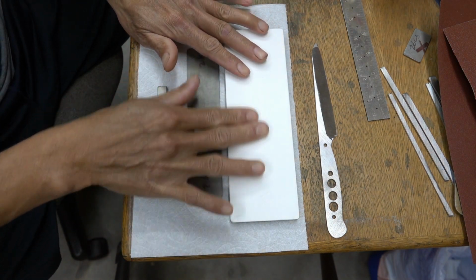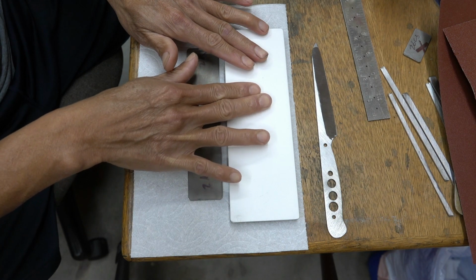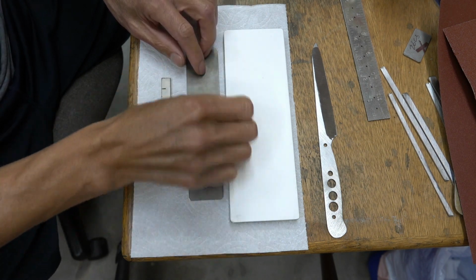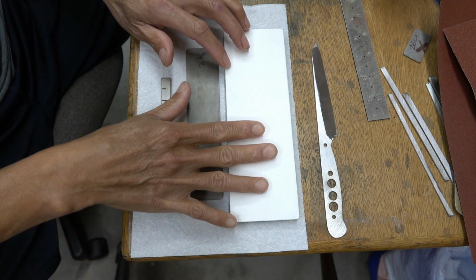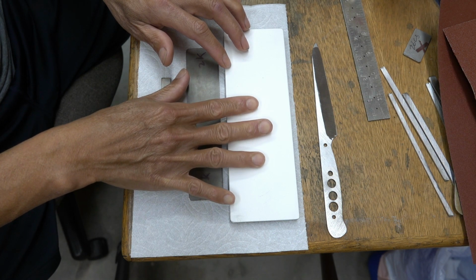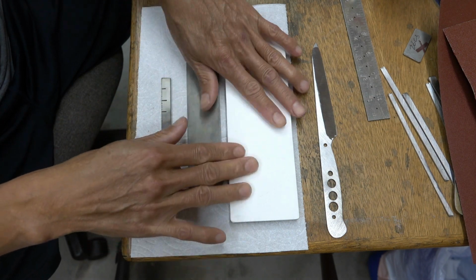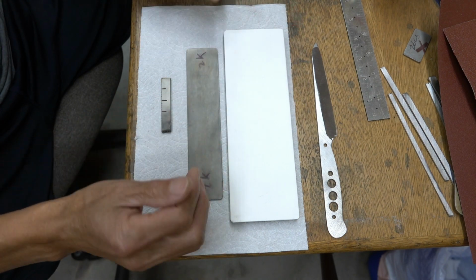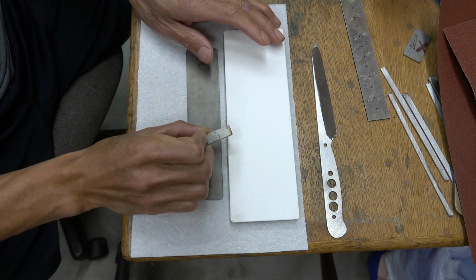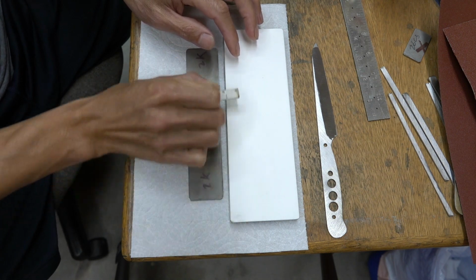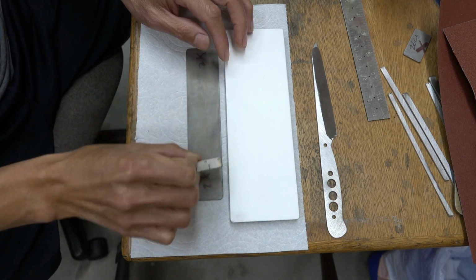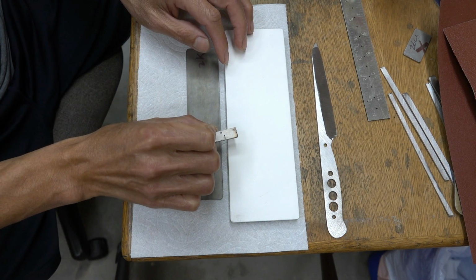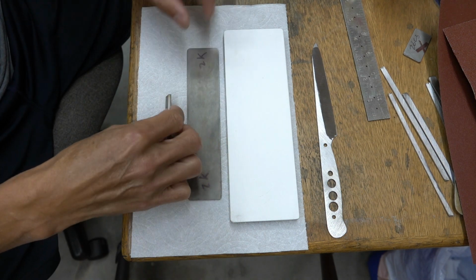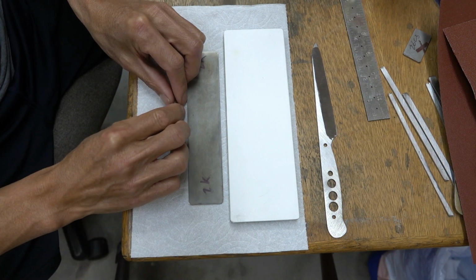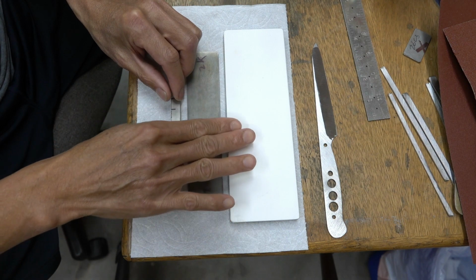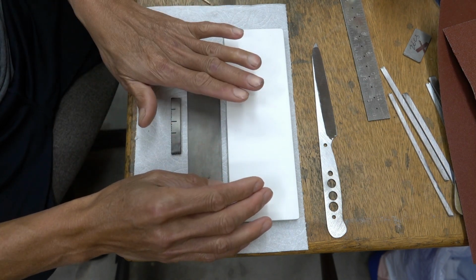What happens when you rub against this surface, or you use the Nagura stone to break up the surface, is that some of the abrasive is loose and some is fixed, embedded into the stone surface. When you rub, I first do a crosshatch, in other words this way and then this way, then at an angle, and then clockwise and counterclockwise. To see what happened, this is more like abrasion. So we see what happened to the carbide in the surface.